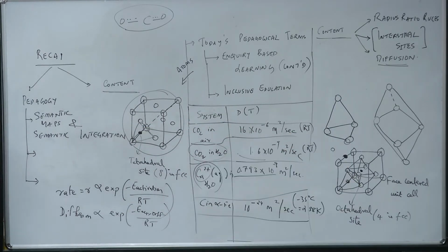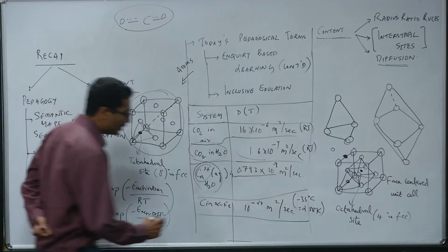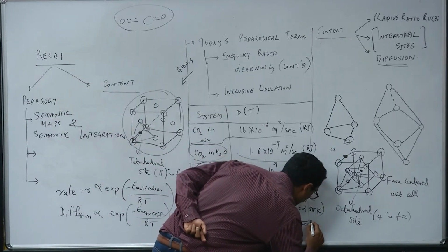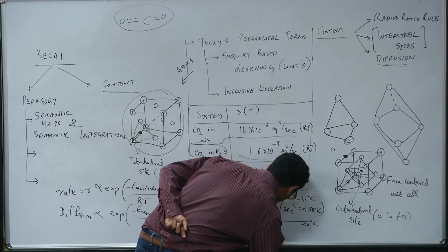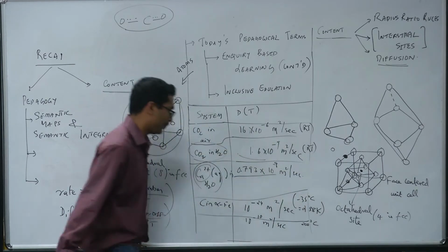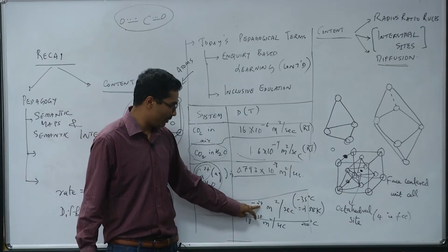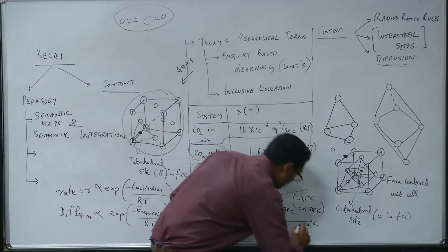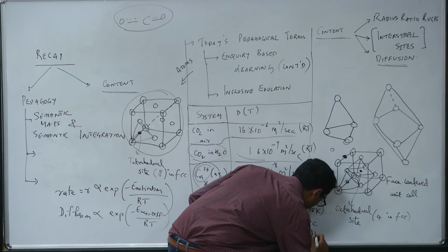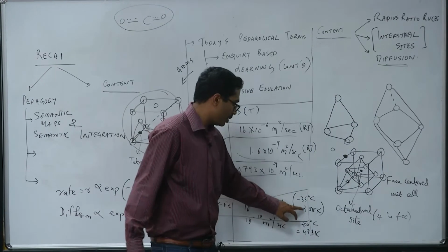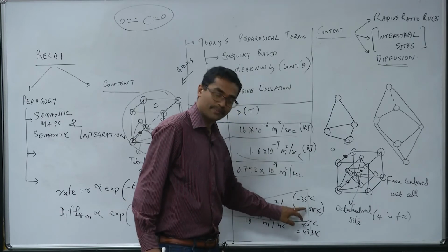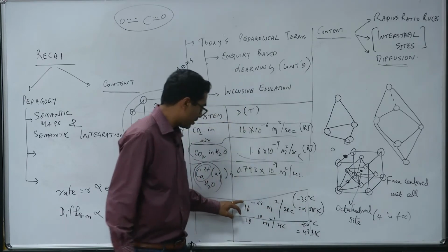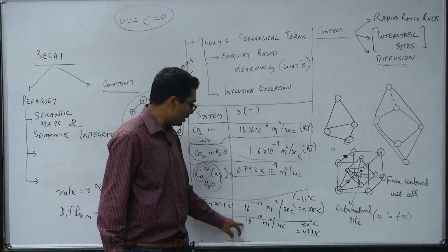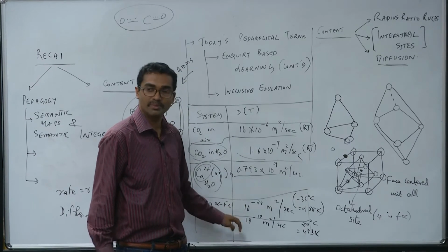At 200 degrees Celsius, very good. 10 to the power of minus 10. Did you see how dramatically different it is? So you see 10 to the power of minus 24. 200 degrees Celsius is basically 473 Kelvin, in absolute scale. So you have increased this temperature by twice, but look at it. You have improved the diffusion coefficient by 14 orders of magnitude.